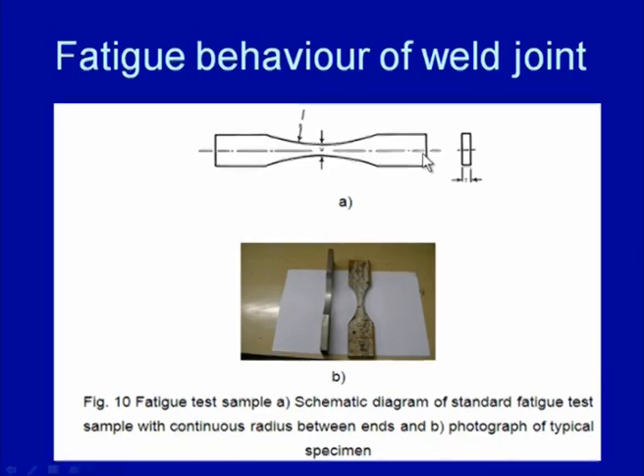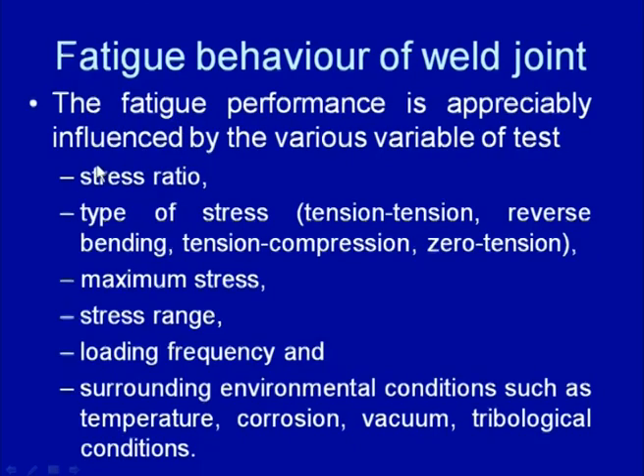So, these are the typical specimens which are used for conducting the fatigue test, and here this is the schematic diagram showing the reduced radius specimen, and this is a real photograph of the reduced radius specimen for fatigue testing. And when the fatigue test is conducted, it is important to see what the loading conditions being used are. So, the fatigue performance, we know, is appreciably influenced by the various parameters related to this test.